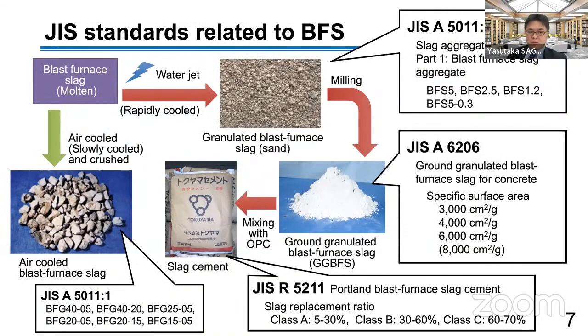So I would like to share the information about the JIS standard related to blast furnace slag. Molten slag is a byproduct in the steel making process. As you know, blast furnace slag is a byproduct, but it was a very precious material for concrete technology. When molten slag is rapidly cooled by water jet, granulated blast furnace slag is generated. It is similar to sand. JIS A 5011 Part 1 specifies slag aggregate, not only slag sand but also slag coarse aggregate. Slag coarse aggregate is produced by a slowly cooled and crushed process.